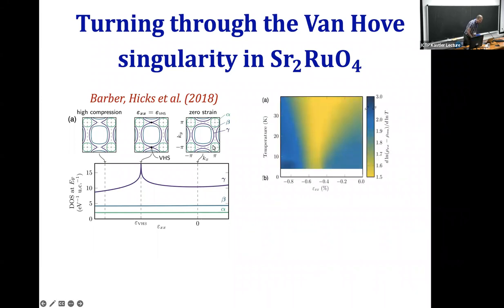Okay, and this is a plot of the logarithmic derivative of the resistivity as a function of temperature and as a function of strain. Okay, so here's zero strain. This is where the Van Hove singularity is. That's actually been confirmed by ARPES measurements as well. And this is temperature. Okay, so you see this beautiful fan-shaped behavior. So it really looks like a quantum critical point. It is a quantum critical point, but presumably a very trivial one. It's just the Van Hove singularity. And what you see here very clearly, okay, if you look at the exponent of the resistivity as a function of temperature, it's close to T squared on either side of the Van Hove singularity, but close to the Van Hove singularity and in this quantum critical region, it actually deviates and it looks like somewhere close to 1.5.